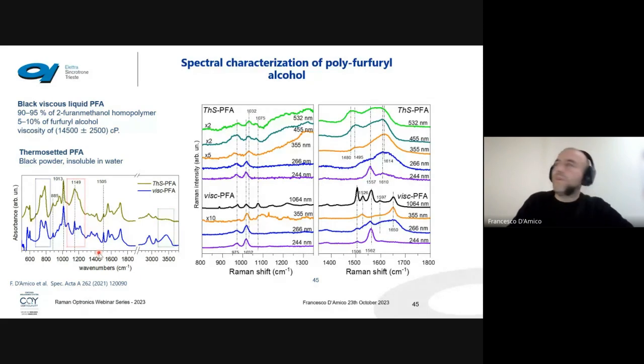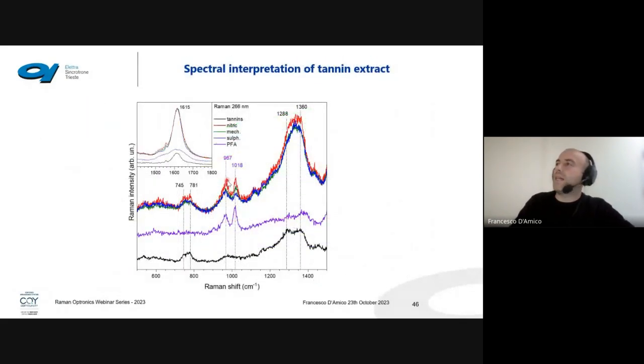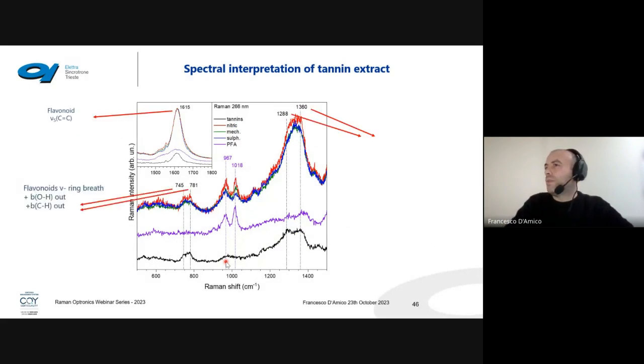But if we employ UV Raman, we recognize that we have strong differences between these two samples, passing from visible to the ultraviolet. In particular, in the ultraviolet we found that all the peaks disappear, and we have only these two peaks that are more intense in the thermoset than in the viscous one. The ratio between these peaks gives information on the polymerization. Therefore, we can do measurements of tannin extracts at 266 to recognize the flavonoid contribution. These two peaks belong to the flavonoid ring breathing.